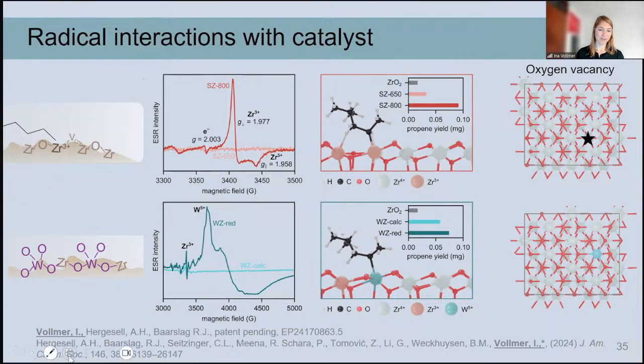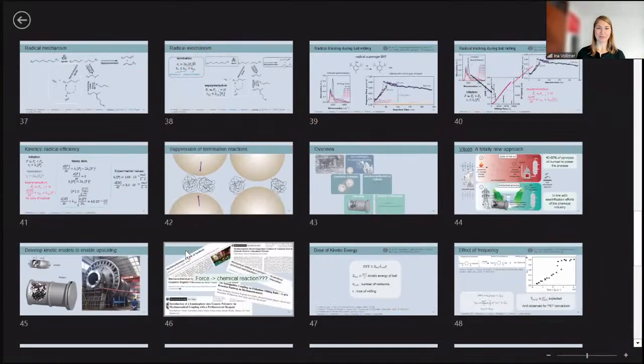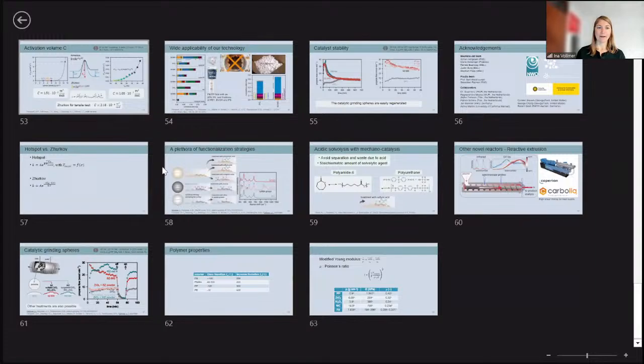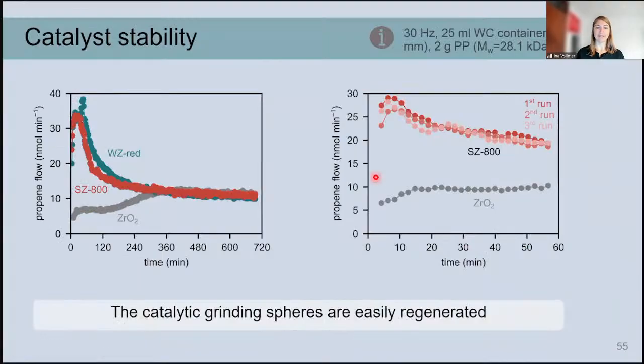Yeah, I tried to show this already a bit in the very end, because this is, of course, a very important question. So this was this slide. You can see that after a few hours, it does. So after around 5 hours, the surface likely completely rubbed off. And we also have SEM images of that. And we see that the surface was quite rough before the experiment, and then after the experiment it becomes more smooth. So we definitely need to find a way to have spheres that regenerate the active surface upon milling.